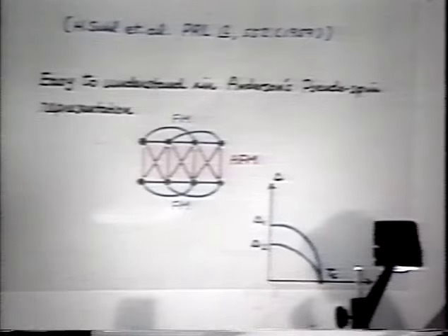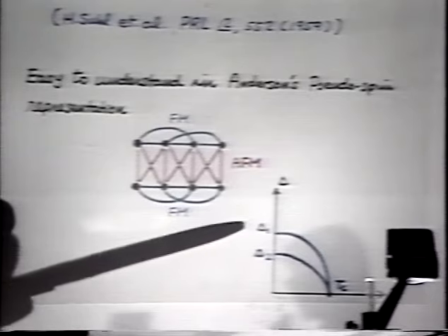In such a model, at temperature below TC, there are in general two gaps, and those gaps vanish at the transition temperature. In general, one gap will be greater and the other will be smaller than the BCS value. So, we find the interband scattering a very appealing mechanism to enhance TC. A, because regardless of the sign of V12, it enhances TC, and B, because it is not a density-density interaction, therefore a strong V12 does not introduce a charge density wave instability as in the usual intraband case.